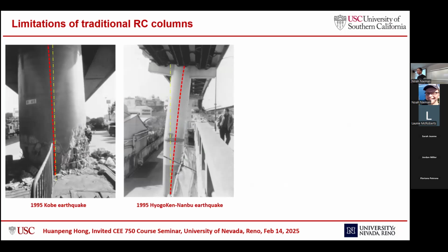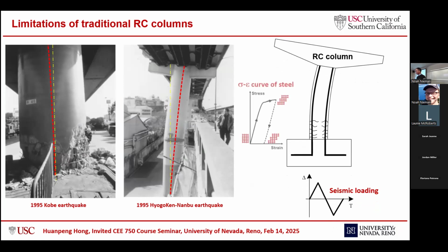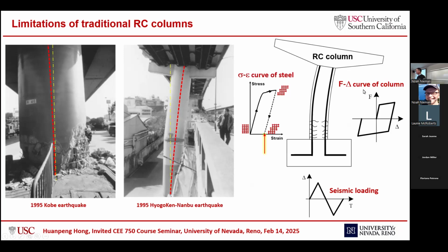The reason why we need to use shape memory alloy in bridges is that conventional reinforced concrete columns have some limitations. After earthquakes, the bridges may not collapse, but they will have really large permanent drift, such as the drift here. This is because of the stress-strain behavior of conventional steel. After unloading, the steel will exhibit a lot of plastic deformation, and this residual strain yields the final force displacement curve of this column looking like this. So there will be large residual or permanent drift of this column. Even though the column has not collapsed after the earthquake, if the construction, reconstruction, or transportation is affected, we still need to demolish it. So that's why we need to reduce the permanent drift of these columns.